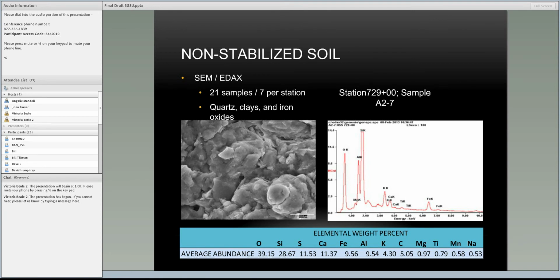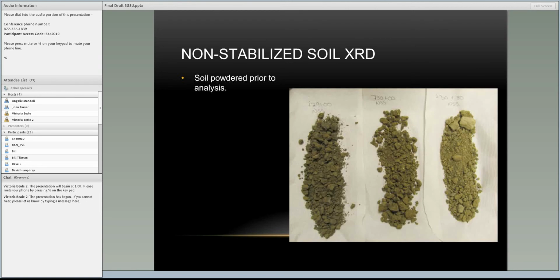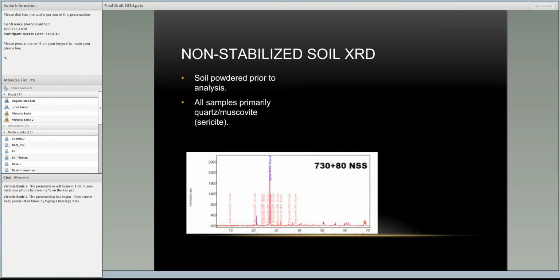And this is a picture of just soil, how we would put it out to air dry. If it was an SEM sample, I might take one of those little pieces that looked interesting or break off a small piece from a larger area. If it was XRD, then the sample would get ground down to a very fine powder. And with the XRD, looking at non-stabilized soil samples, the samples were primarily quartz with muscovite, and you can see that big quartz peak, the largest peak at the top there, with the smaller peaks being the muscovite.